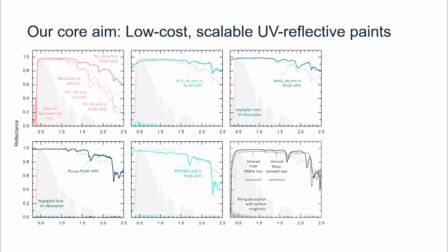They're aluminum oxide and barium sulfate, both quite low cost and easy to acquire in powder form for, really, cents a gram. What you see is that they overcome that dip in reflectivity that you see with the titanium dioxide. That's right here. So you see that solar absorption that occurs with our traditional white paints is now gone because the aluminum oxide and the barium sulfate just reflect over that part of the spectrum. And that, it turns out, is the key to making a white paint a super white paint that is capable of this passive cooling effect.